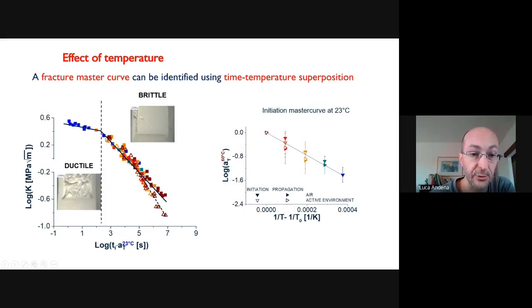Actually, it turns out that you can try to superimpose all the data together by applying time-temperature superposition, which is a well-known reduction scheme used to treat mechanical properties of polymers. Basically, it means that you can shift curves at different temperatures to obtain a single master curve. And you can see that the shift factor, which is the amount you need to perform this translation, indeed turns out nicely for all the conditions.